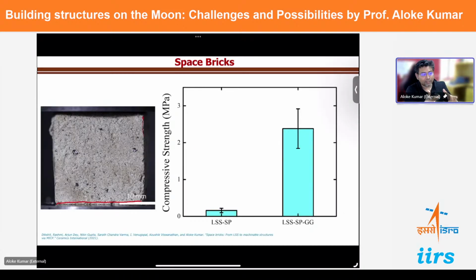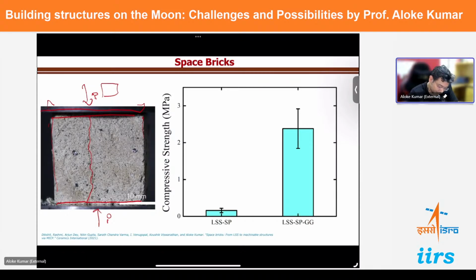So you remember the casts we were showing. So this is a nice, it's a cube-like structure. You can see at the top. There are forces being applied from the top and the bottom. So it is being compressed. Okay. And this is to determine experimentally a compressive strength. So I'll just play this in a video, and we apply compressive strength on this brick-like structure. And you can see now that there's a crack that has grown, right? So if you apply too much force, this brick-like thing breaks.